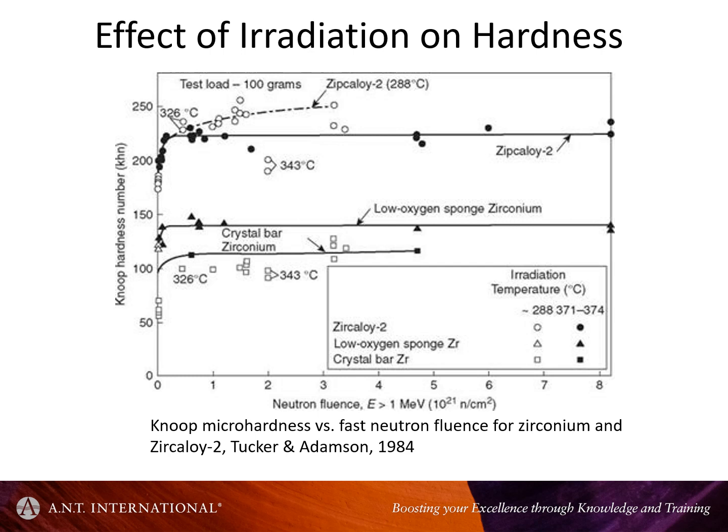So what you see for many zirconium alloys as a function of neutron fluence or dose or displacements per atom, however you want to look at that, is the hardness increases very rapidly at the beginning of the radiation and then reaches a more or less steady state saturated value at very low doses, which is around 0.03 dpa in many cases. In terms of fast fluence, it's about 2 to 4 times 10 to the 24 neutrons per meter squared.